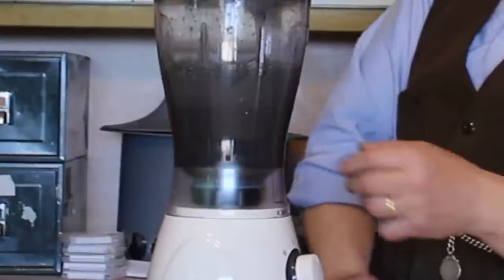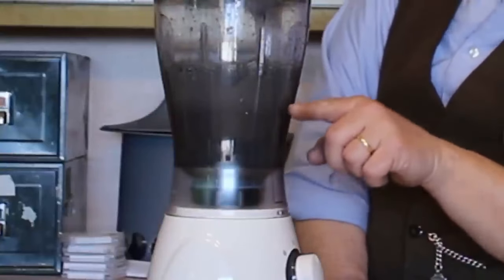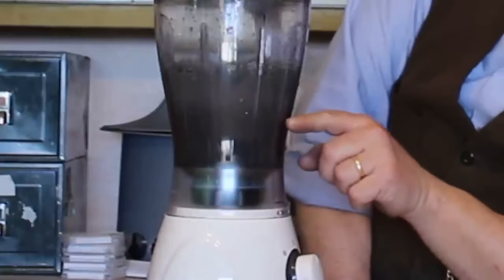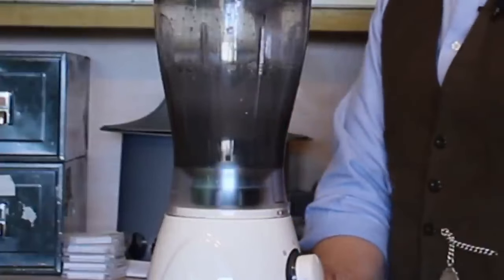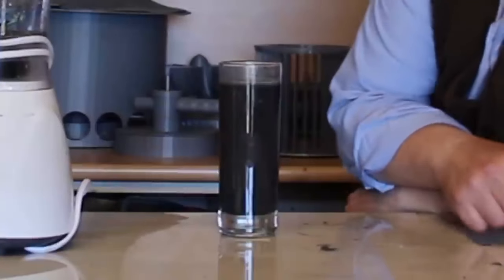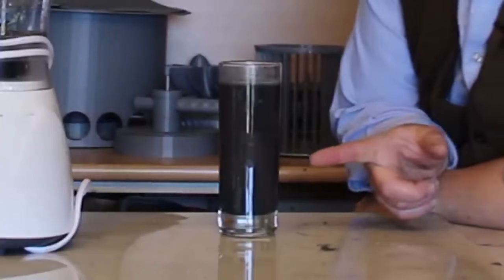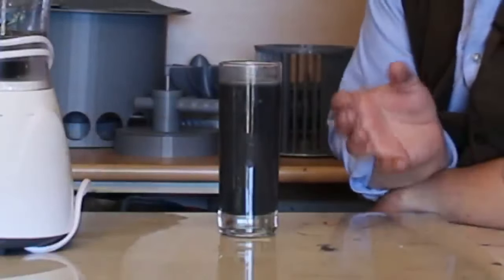So the gas will just come out of the foam. The heavier particles of graphite are going to sink to the bottom, and we're going to get a black layer in between, which is the graphene. So I've scraped off some of the foam and there it is. It's kind of a blue-black colour. Apparently it's stable in suspension for about 2 months.